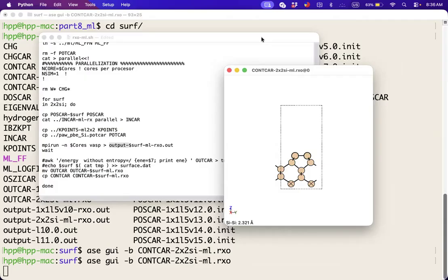So in this case, what we did is only to have some initial guess of the structure, because now we have to put the hydrogens to train the machine learning again, and after that we do the next verification only with the machine learning. In fact, we're going to raise the temperature to 400 Kelvin, and after that drop it to 0 Kelvin, and after that we are going to get the actual structure, do the final ab initio relaxation, and that's it. That will be the process.